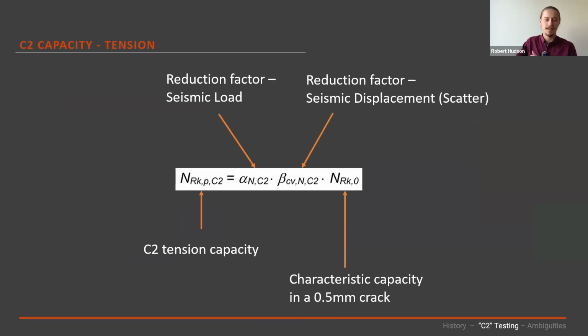Now, I apologize to anyone who's run this testing, because I'm going to oversimplify this a little bit. The test procedure is the most complex post-installed anchor test procedure I am aware of. But when you're trying to calculate a C2 tension capacity, it basically boils down to this formula. Oversimplistically, but basically it does. What we have on the left there is the C2 tension capacity. We have these two reduction factors, alpha and beta, and then we have this baseline capacity that we start with.